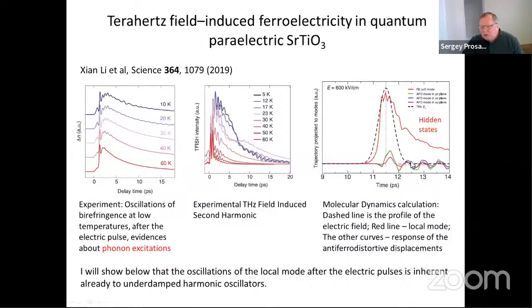Here we also see oscillations at the bottom of some antiferrodistortive order parameter after the pulse. This is also an interesting feature, that the electric pulse excites not only polar phonons, but there are other oscillations related to non-polar modes.